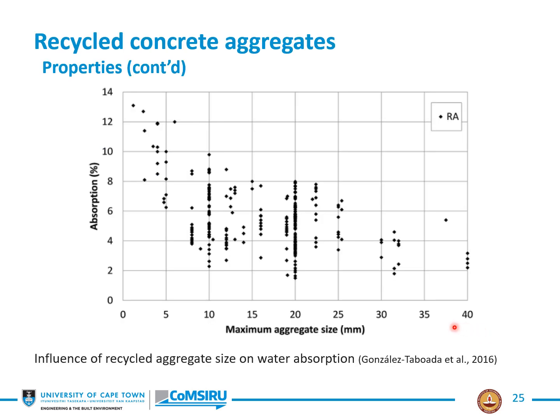Here we are plotting absorption versus maximum aggregate size. And although there's a large scatter of data here, there's a clear trend that as the maximum aggregate size increases, so the absorption comes down. Now, for normal crushed hard rock aggregates, bear in mind that the absorption is typically a maximum of around 1%. Normally in South Africa with our hard rock crushed aggregates, we're at around about 0.5%, so quite low. So even with this size of aggregate here around 20 to 25, you can see that the absorption can be considerably higher than natural virgin aggregates crushed from hard rock.